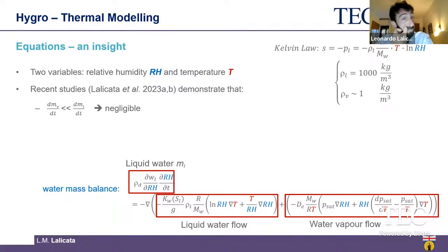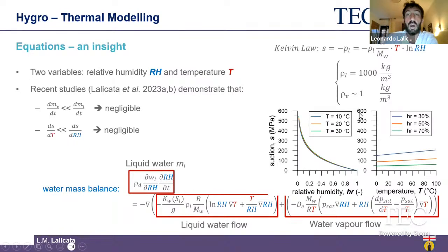The other aspect I have been focusing on is the Kelvin law here. You see, suction depends on both temperature and relative humidity. But if we plot this equation, we find that the suction really depends on the relative humidity. It changes by about 550 megapascal over the whole range, while on the other side, from 0 to 100 degrees of change in temperature, the changes in suction are really modest compared to the changes induced by the relative humidity. In mathematical terms, this means that the variation of suction due to temperature is much smaller and negligible compared to the changes in suction due to the relative humidity.